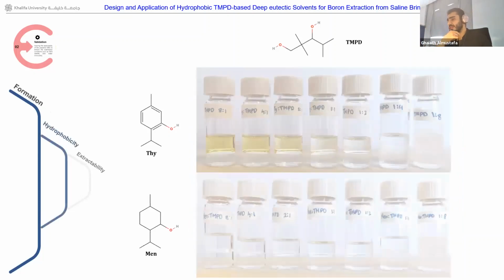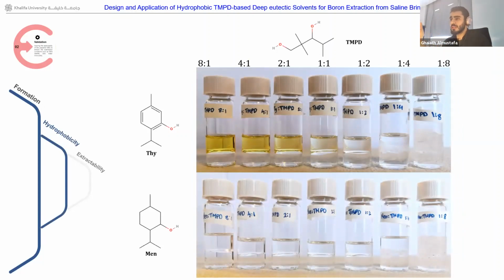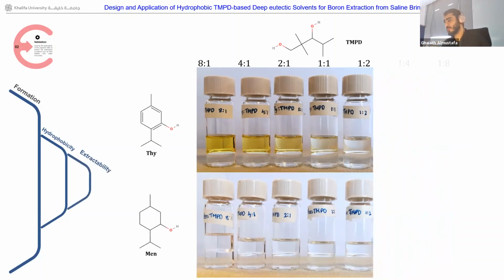Now, for the hydrophobicity, we mix those components in a 1:1 ratio with plain DI water to see how stable they are. And you can see right away that the components with TMPD ratio 8 and TMPD ratio 4, for both thymol and menthol, have solidified, and they were not stable. So we exclude them immediately from the liquid-liquid extraction studies.